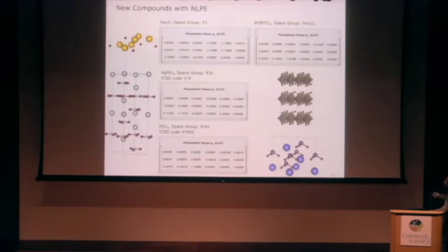And this layered structure also has very negative E33, -7.4 coulomb per meter square. And these 2 compounds have already been synthesized. They're known compounds with pretty decent negative E33 as well. But as you can see, they're not perovskite structures.